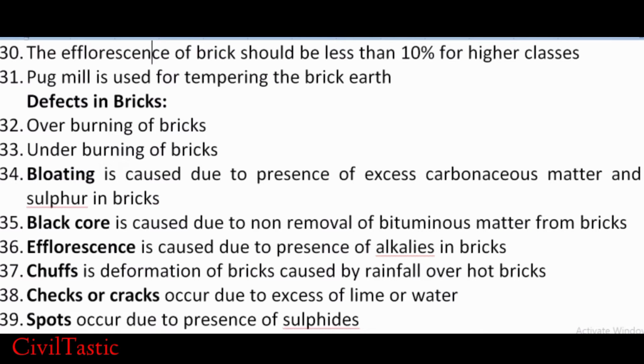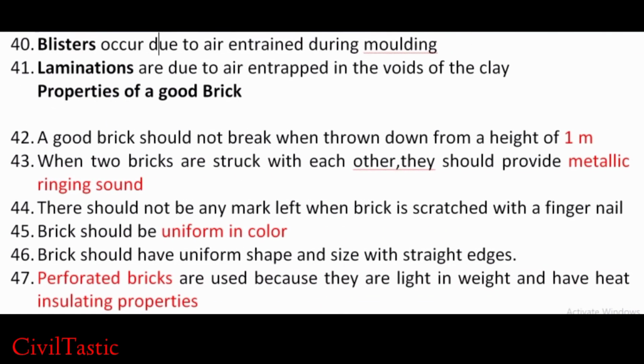Spots occur due to presence of sulfides. Blisters occur due to air entrained during molding. Laminations are due to air entrapped in the voids of the clay.